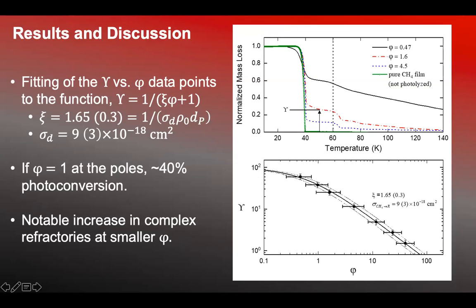So when you go through and take this data, you actually get a curve of the mass loss versus temperature. Pre-experiment, there's a deposition of this methane, and then you go through the experiment, and with varying different phi values here, you actually get a certain amount of this photolyzed methane. In other words, certain compounds, including ethane, and then some more complex things remaining in the deposited ice.